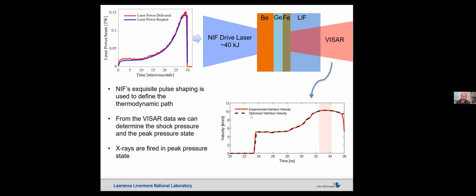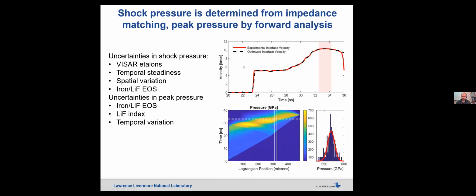So then the way we obtain the pressures is we perform a forward optimization and iterative forward analysis, which Suzanne Ali has published a technique on how to do this to obtain those peak pressure states. I won't go through too much in detail, but if you have questions about the uncertainties, please let me know. So again, we do a hydrocode optimization to match the input pressure drive to the output interface velocity, which allows us to accurately constrain what the pressure history in our sample was.